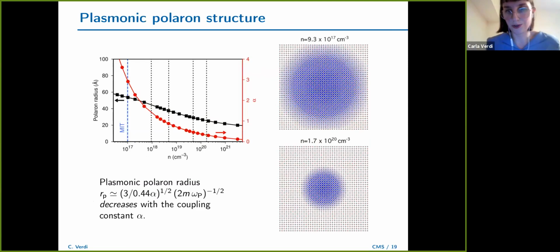We actually wanted to do something more. They asked us to try and estimate what would be the plasmonic polaron structure. So we tried to do this using many-body perturbation theory, and we actually kind of failed. So what happens is that if you use perturbation theory, you will never achieve self-localization. You will get a polaron wave function that gives you an increased probability of finding the electron near the center, but then you will always have a still finite probability of finding the electron at infinite distance from the center. So the only thing that we achieved to do was to use a model.